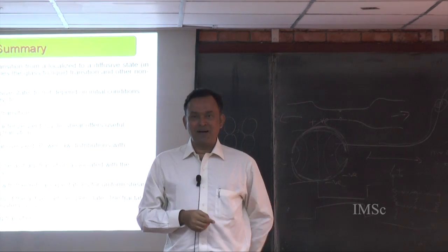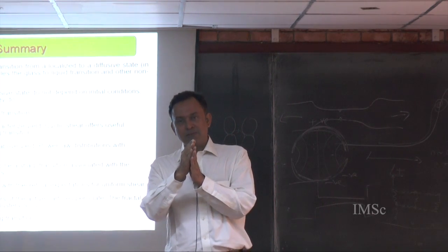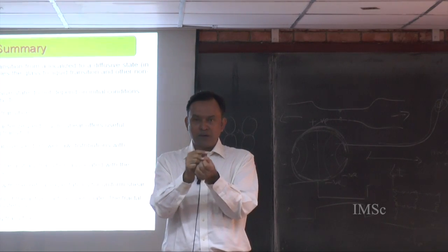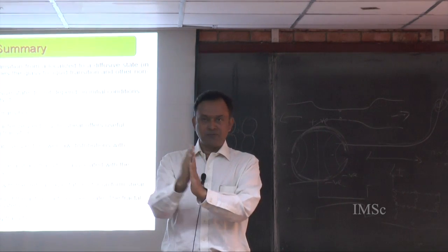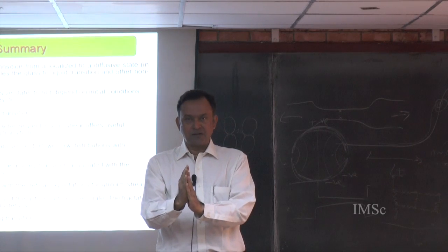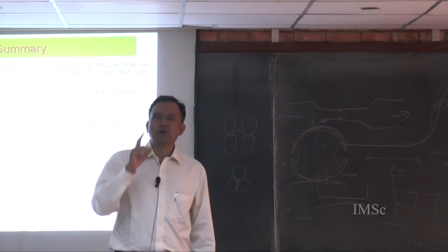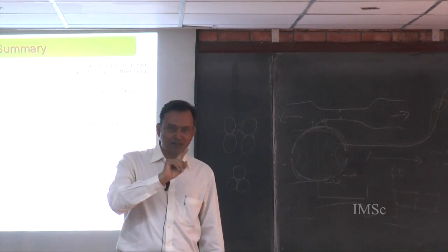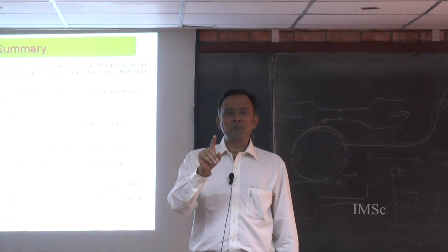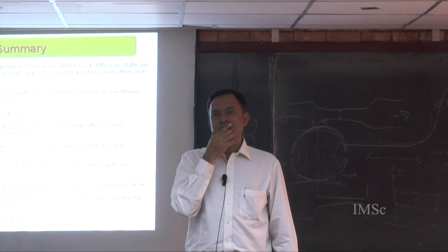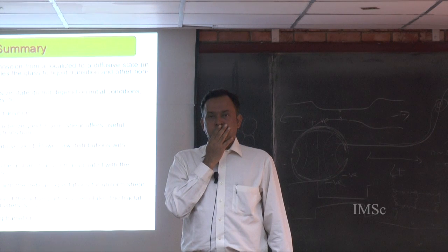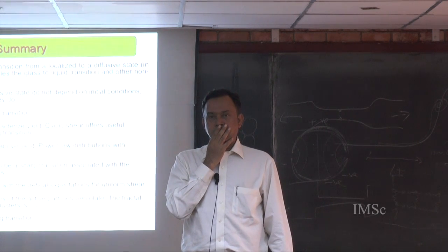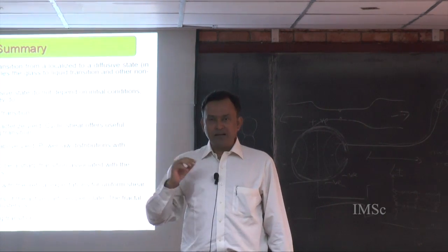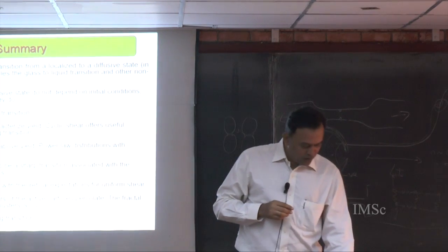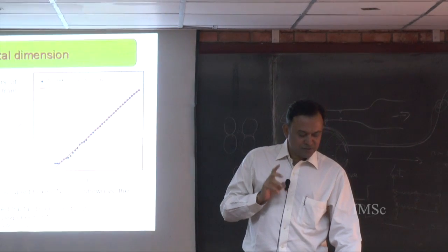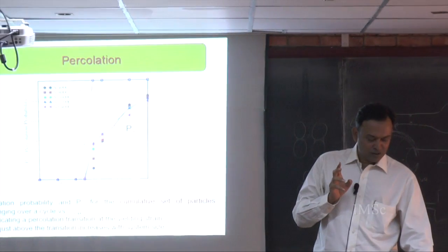Whereas in terms of where we are looking at that energy, it's when you reverse back to zero strain. Sorry, you asked - no, it's not at the residual strain. Beyond the critical strain, the minimum shifts out, and then it's no longer at gamma equal to 0. So the data that I showed was for zero strain at the end of each cycle always.